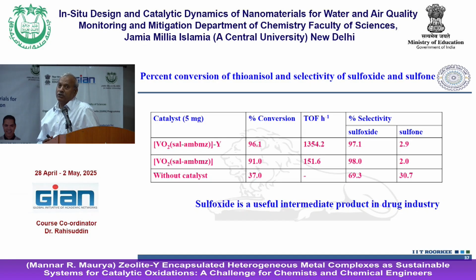The desired one is only sulfoxide, but in some cases it gives some percentage of sulfone. When you do it without any catalyst in the presence of oxidant, you will see that the result is very different. It means our catalysts are becoming more selective towards the sulfoxide, not the sulfone. So we are getting a good amount of at least sulfoxide.